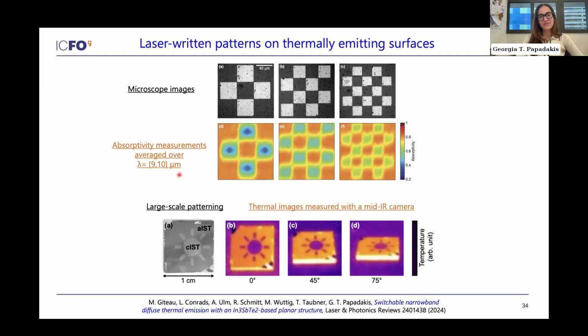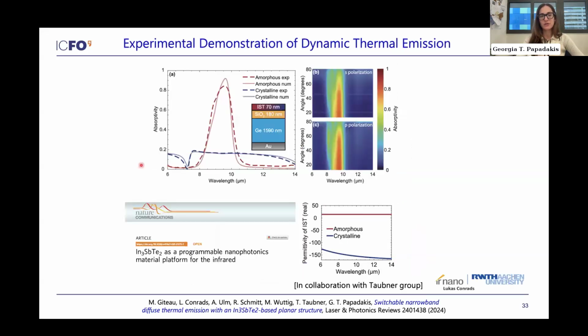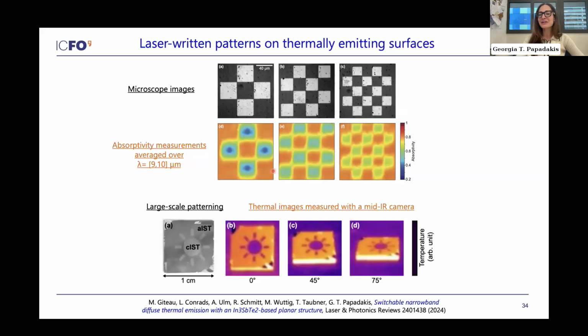And then we took FTIR images, absorptivity measurements, that we averaged over a short wavelength range where the material emits, from 9 to 10. And you can see here that this structure, which has the same temperature across it, looks like certain areas emit more than others. This is simply because of the IST on top having different characteristics.